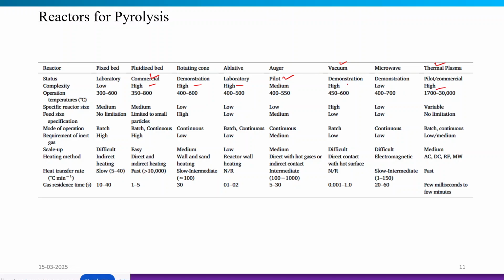Also in the case of the thermal plasma and vacuum reactor, at a very high temperature condition the thermal plasma reactor is operated, and microwave is slightly lower than that. When we consider reactor size, the reactor size is bigger for the vacuum reactor, and the mode of operation is batch in some cases, and in most cases it is a continuous process like rotating cone, fluidized bed, auger reactor, and microwave reactor. The thermal plasma reactor can be both batch and continuous mode.